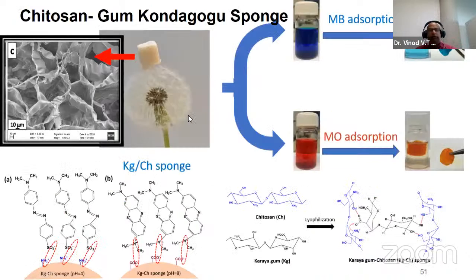Another important research is where we used two biopolymers together, this chitosan and gums combination, for making a sponge. This sponge shows high porosity, and this material is easily used for dye adsorption from water. We have shown the adsorption of methylene blue and methyl orange from water, and this showed very excellent results.